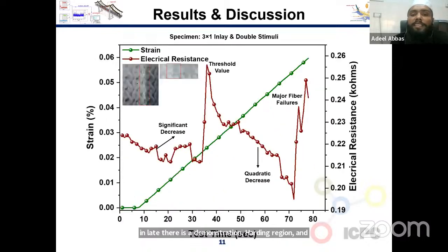Similarly, changing the stacking sequence to 3 by 1 inlay with double stimuli layer, we can see that there is a significant decrease in electrical resistance during initial mechanical loading, and this can be related to the decrease in electrical resistance of wires on bending, because the electrons with low velocity drift are capable of moving through the bent wire, and electrical resistance is decreased, and the same was the case with the carbon fiber.